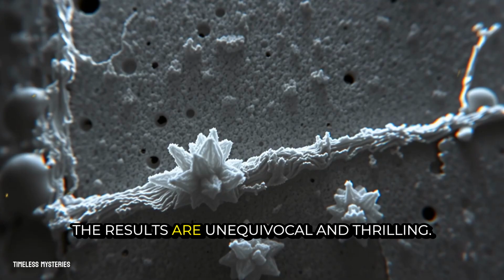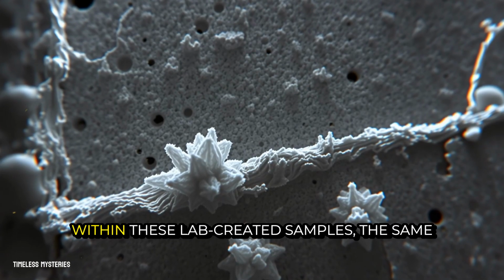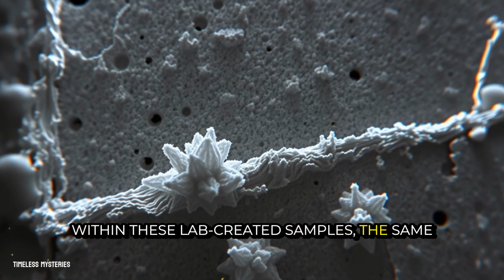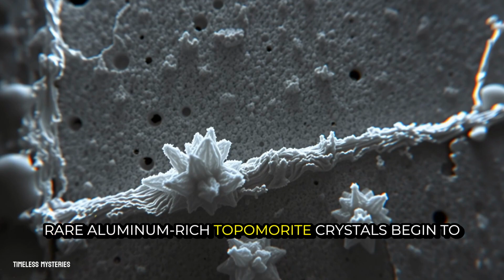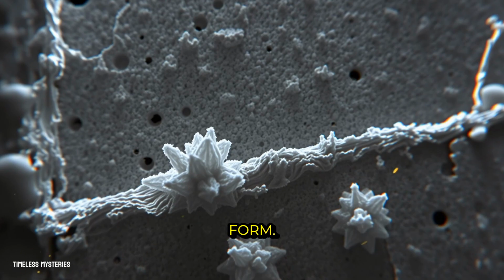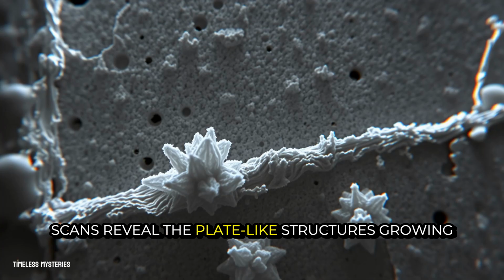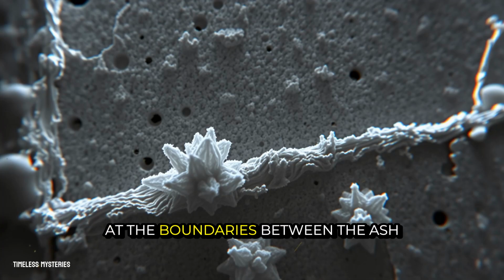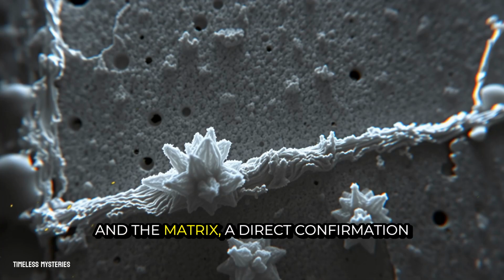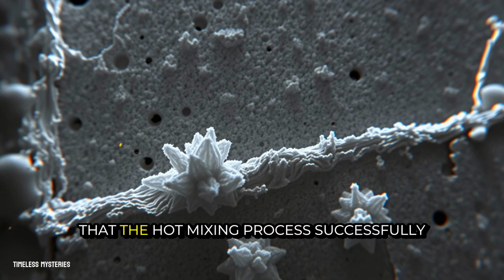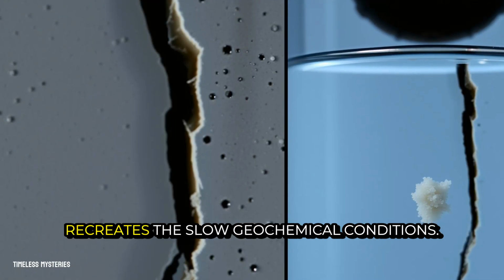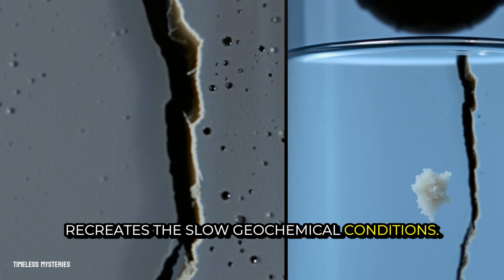The results are unequivocal and thrilling. Within these lab-created samples, the same rare aluminum-rich Tobermorite crystals begin to form. Scans reveal the plate-like structures growing at the boundaries between the ash and the matrix, a direct confirmation that the hot mixing process successfully recreates the slow geochemical conditions.